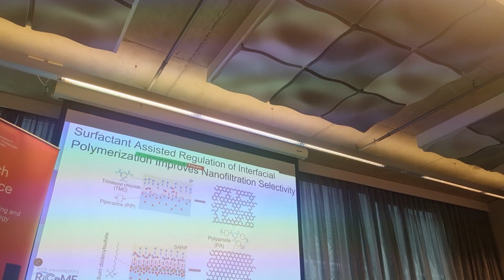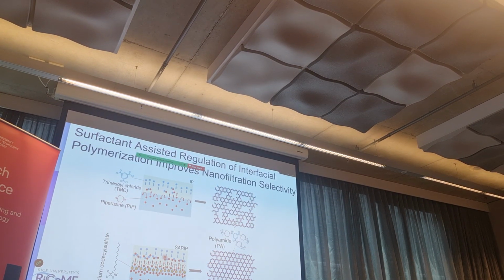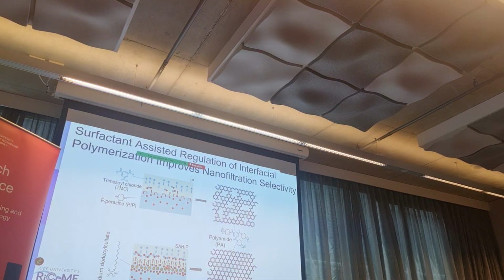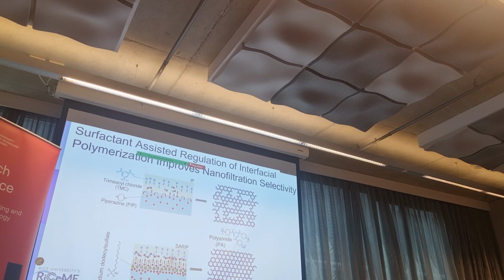The sodium dodecyl sulfate migrated to the interface of the water-oil interface, with the tail in the organic phase and the polar head at the interface. By doing so - if you read the paper, there are details proved by simulations - the interfacial polymerization was more controlled, and you were able to get more uniform pore size. We quantified the pore size.